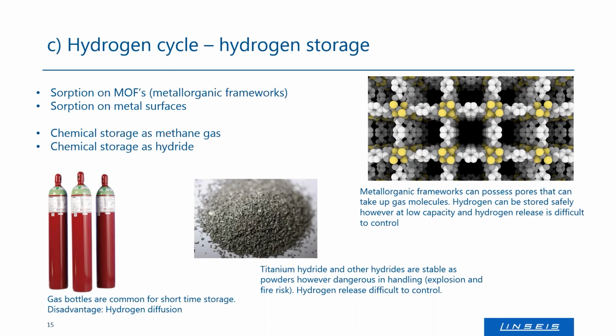And besides that, there is also the possibility to do chemical storage, which is, in my opinion, the safest way to handle it. If you react it with other molecules like nitrogen, you can form ammonia and use the ammonia as a medium to store and transport it. You can also make it react with some metals like titanium. Titanium can form a hydride, which is more or less stable. There's no leakage, no hydrogen released if you do not lower the pressure and if you do not increase the temperature. And that's the chemical storage that's already going on.